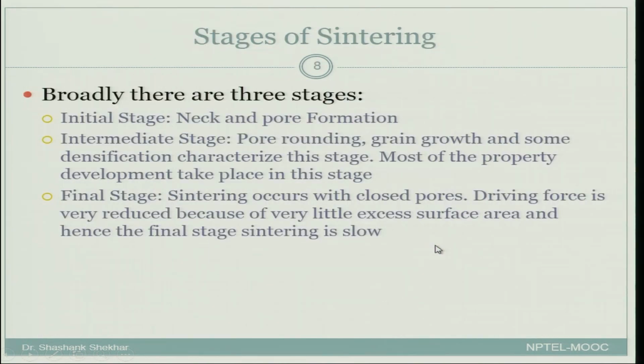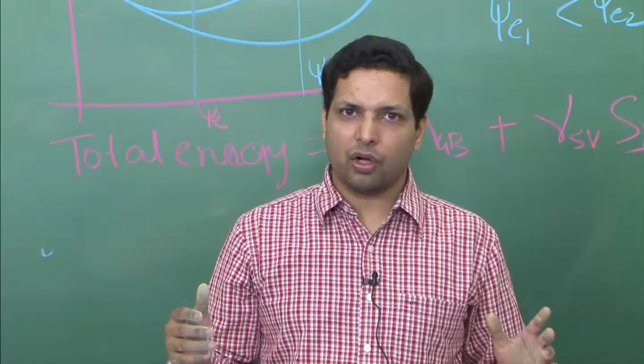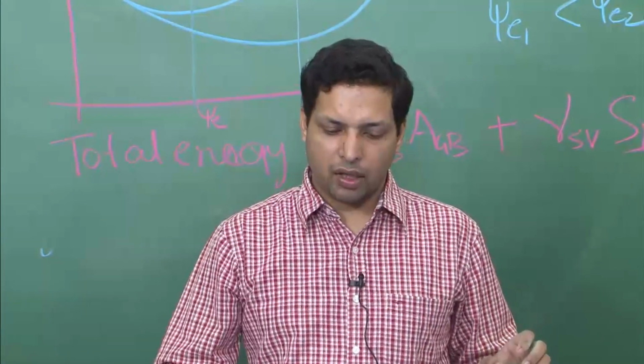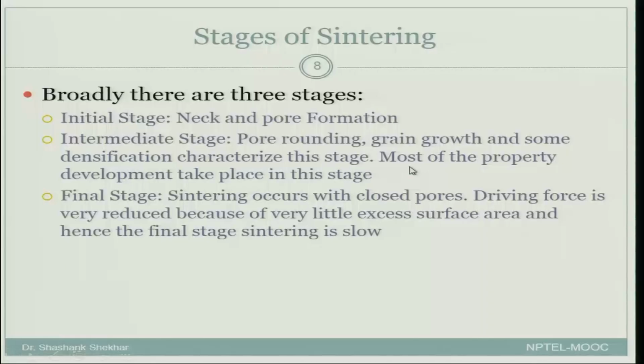Now, it is time for us to take a look at stages of sintering. Broadly, there are 3 stages of sintering. In the initial stage, you have neck and pore formation. So, the particles will stick to each other, they will form neck, and hence there will be a very large network of pores. In the intermediate stage, pore rounding, grain growth, and some densifications take place. So, you will have the pores which were now very large and interconnected all throughout, they will start to round off, they will become rounded in characteristics.